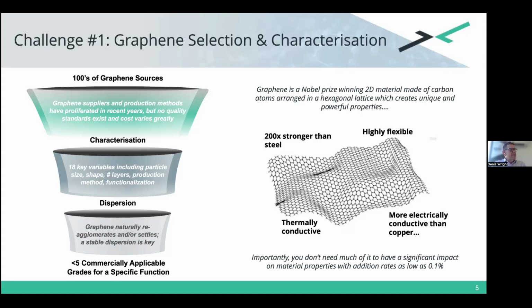Another challenge with graphene is that it agglomerates and settles out. It wants to do that, especially straight graphene, not graphene oxide, or with a high percentage of oxygen in there somehow, or reduced graphene oxide. Through all that work and the hundreds of grades that we've looked at, we've actually got about 5 that work in protective coatings well and reliably. That means that we've got a hit ratio of somewhere between 2.5% and 5%, or even lower than that.